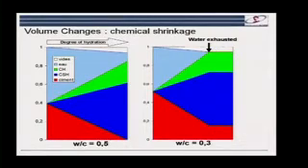The other message in this slide is to see that if we don't have enough water to react all the cement, it doesn't matter. This material here is still going to be stronger at the end than this one here, because strength and nearly all other properties depend on the total amount of water plus voids, total amount of pores that left over. And we see in this case we've got a much smaller amount of porosity here than we have in this example here.